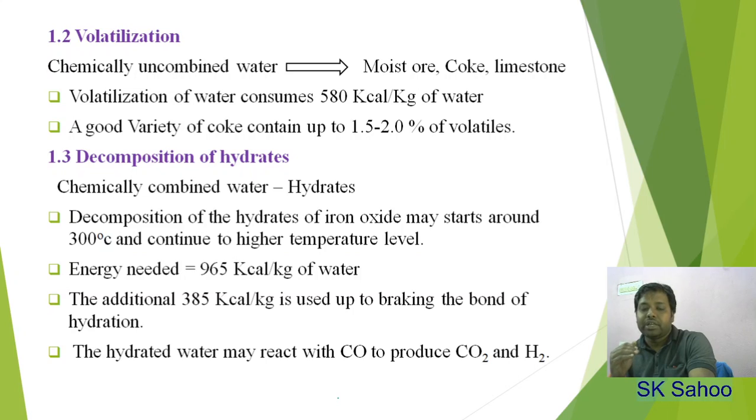The devolatilization of water, that means chemically uncombined water, in the form of moisture in ore, coke and limestone, requires about 580 kilocalorie per kg of water.